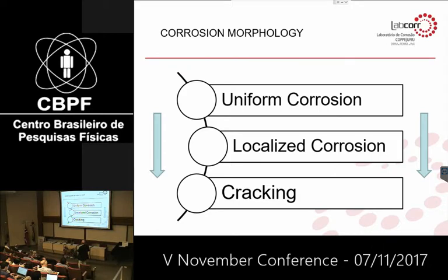And the story does not finish with localized corrosion. There is always the possibility of cracking. It's another morphology, much more critical than localized corrosion. The reasons for cracking are several. We can think about hydrogen effects on the material.